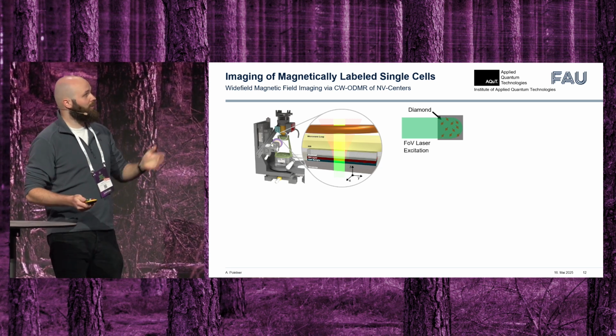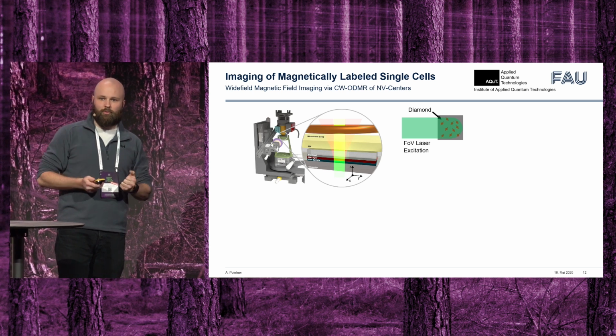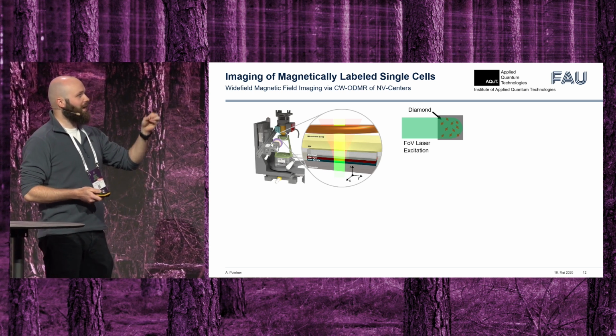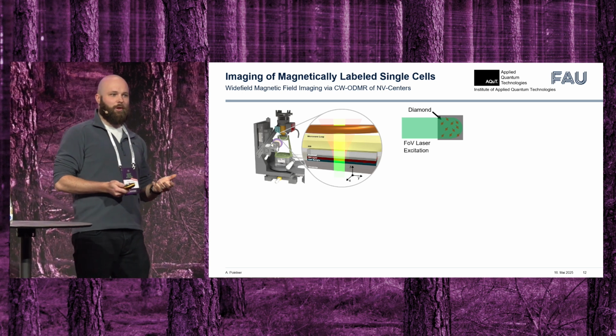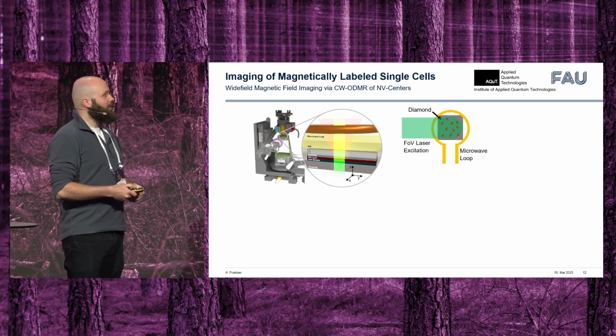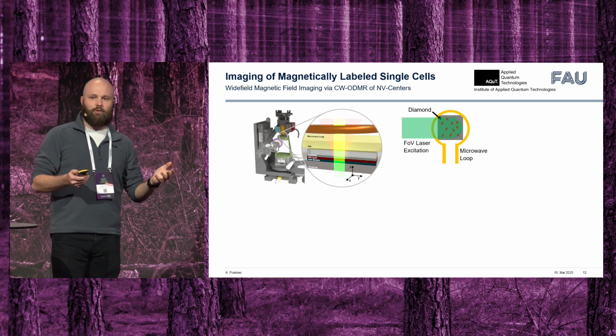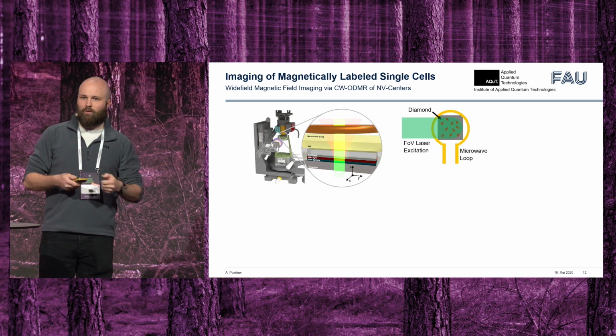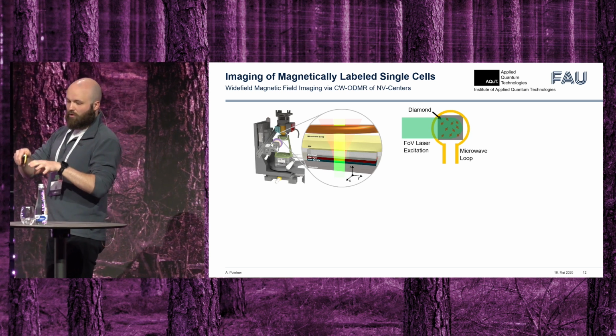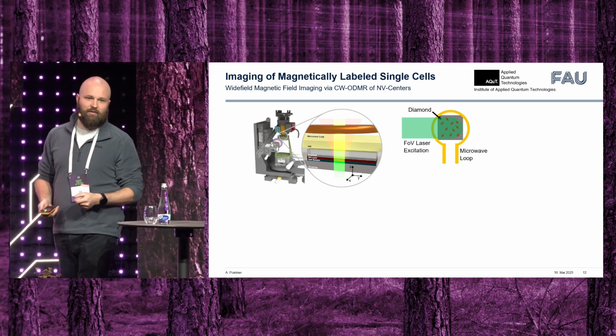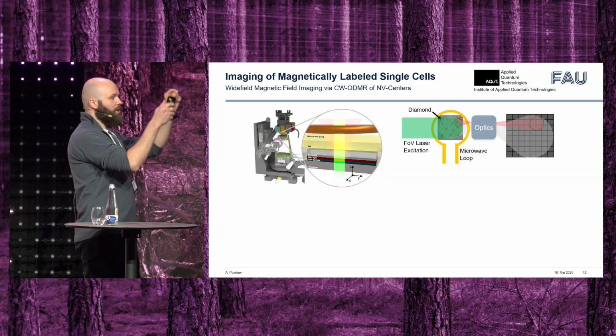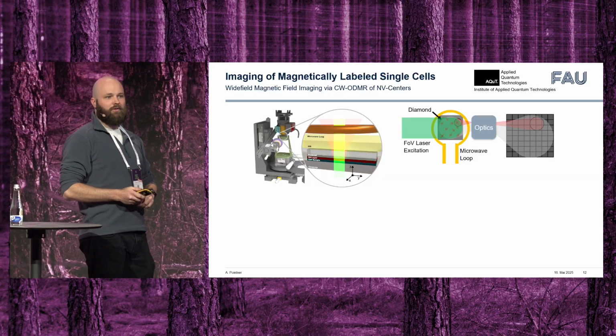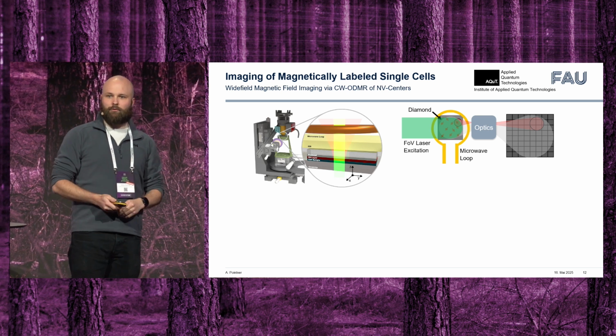And it's interesting to see because you can actually see the diamond glow red in the experiment. And this red fluorescence light is what contains information about the NV center. Then we add a microwave loop because we need a way in order to manipulate the spin state in order to read out the energy levels present at the location of the NV centers. And then we collect all the light and we focus it on a camera sensor. And by using a camera, we can spatially resolve the signal across our diamond, which acts as our magnetic field mediator.